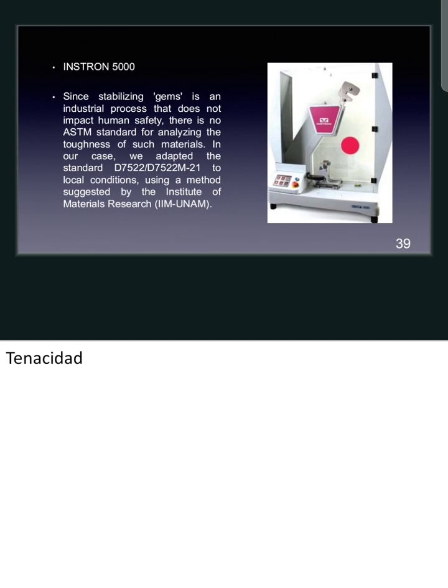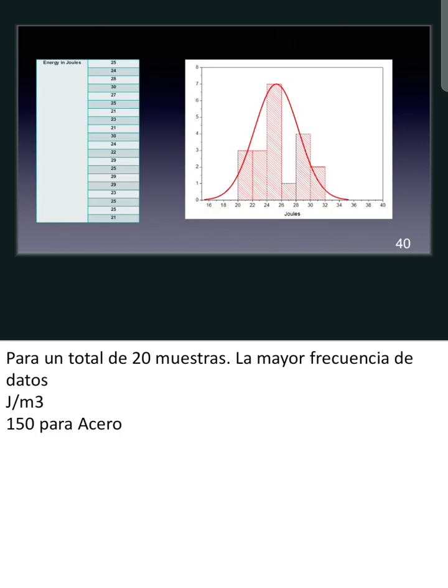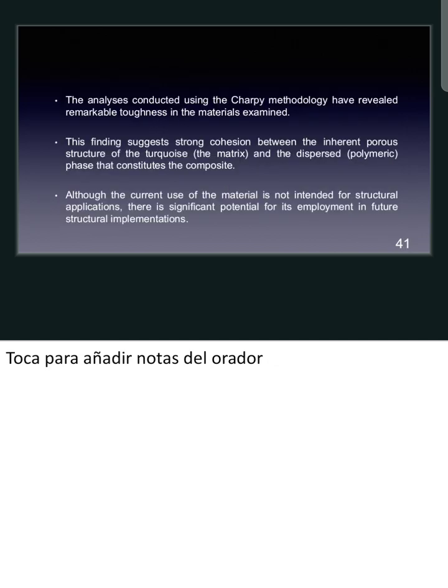Then these same rectangular prisms we used in the Charpy impact test, and these are the results for a total of 20 samples. The highest frequency was about 24 and 26 joules. The analysis conducted using the Charpy methodology has revealed remarkable toughness in the materials examined.